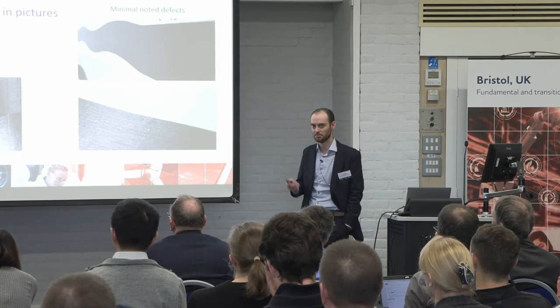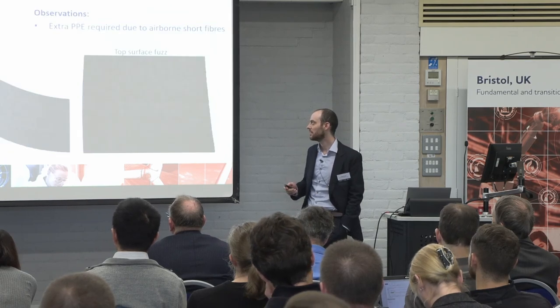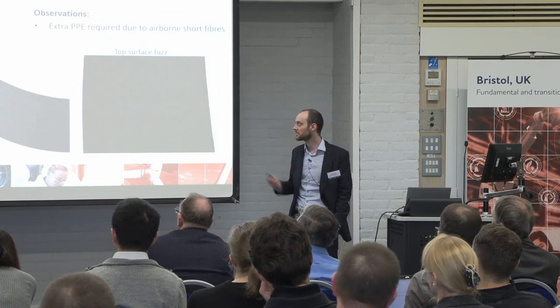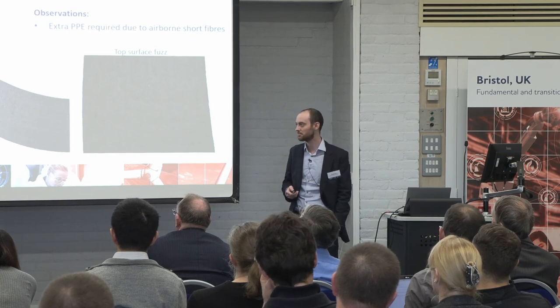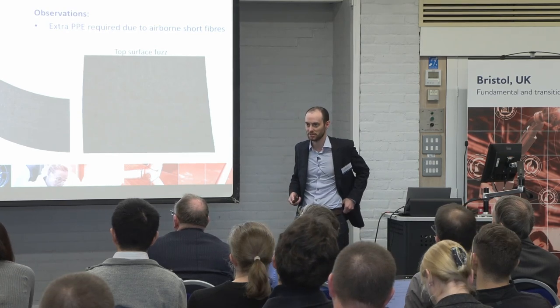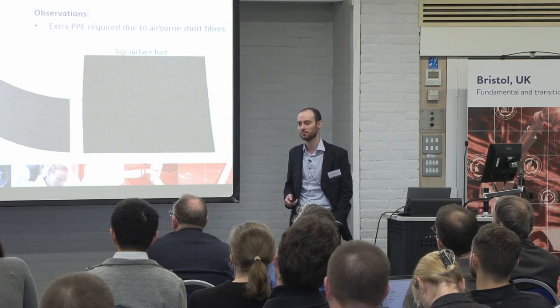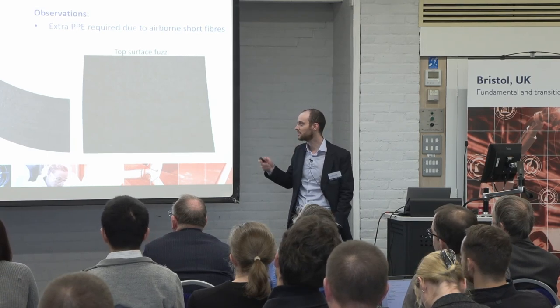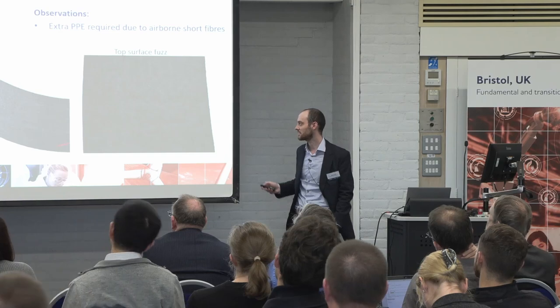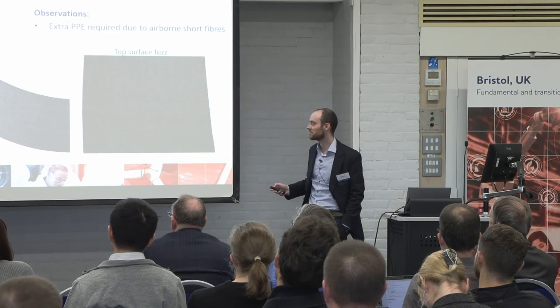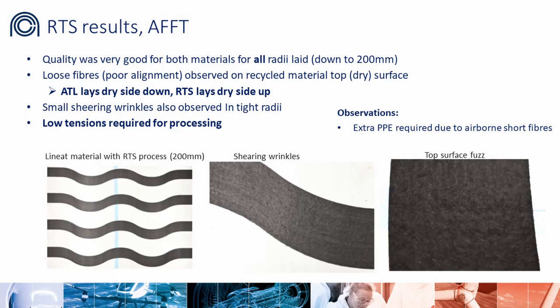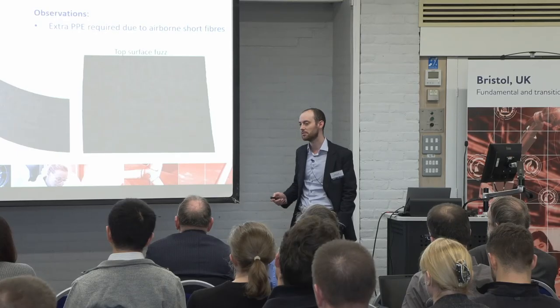But the next test is a much bigger question: can we, and I believe this is for the first time, put a recycled short fiber material through the ATL process? So that's the first time we'd put a recycled short fiber material through an industrial automated tape layup technique. And again, it's quite a boring slide, really, because it was very, very successful. And you can see, if you know the ATL or AFP process, these curves are not possible using industry standard machines. And we were able to do this, or ICOMAT were able to do this with an aligned short fiber material with quite a high degree of success.